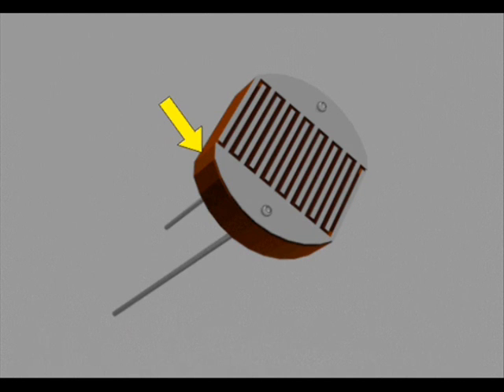The material is deposited in zigzag pattern in order to obtain the desired resistance and power rating. This zigzag area separates the metal deposited areas into two regions. Then the ohmic contacts are made on either side of the area. The resistances of these contacts should be as less as possible to make sure that the resistance mainly changes due to the effect of light only.